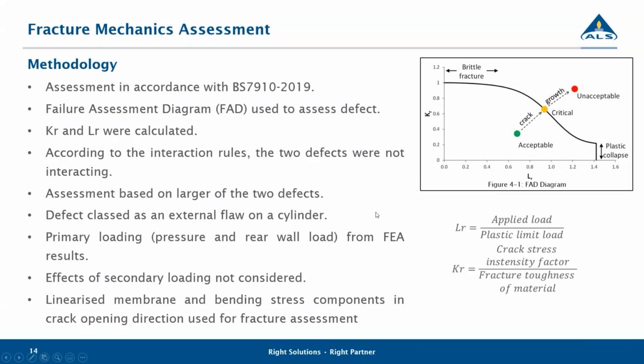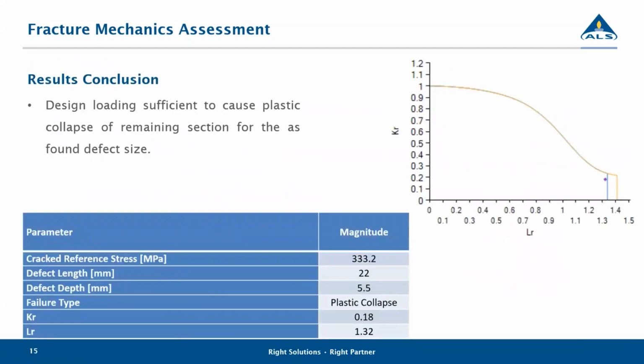The effects of secondary loading were not considered. And we used the linearized membrane and bending stress components in the crack opening direction for the fracture assessment. So the conclusion from the fracture mechanics assessment is that the loading with the defects present is sufficient to cause plastic collapse. If you look at the toughness ratio versus the plastic collapse ratio, allowable versus actual, you'll see that we've got a plastic collapse ratio of 1.32, which tells us that for the defect that we've assessed, plastic collapse is plausible. So that sort of gave us confidence that there's not something else that's caused it in terms of overload, but that with the defects there, and because the tube is highly loaded, those defects could be sufficient to rupture that tube completely.